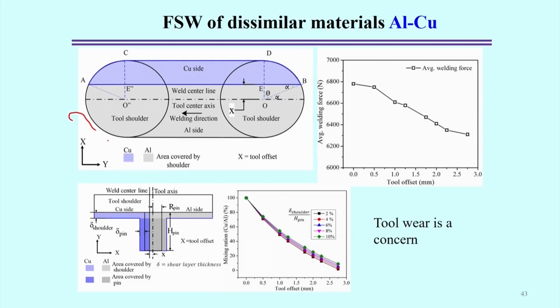So, looking into the volumetric mixing ratio in this figure, the mixing ratio of copper by aluminum, when the tool offset is equal to 0, is 100%, which means equal volume mixing exists at a tool offset of 0. But when the tool offset increases and is raised to around 2.5 millimeters, the mixing ratio decreases. So there is a variation of the mixing ratio. This way it is possible to control, and roughly estimate, the volume mixing ratio, and we can correlate the amount of intermetallic compound formation just by controlling the amount of the tool offset.